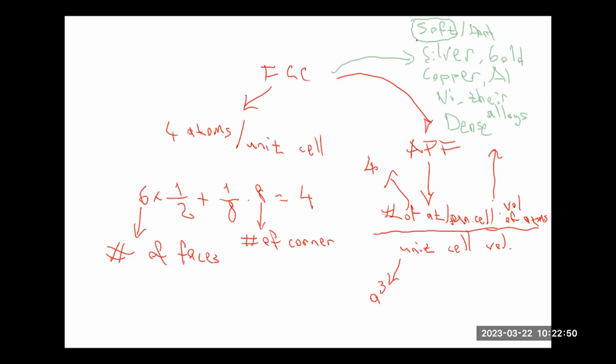So dislocations move very easily. And the critical resolved shear stress values for the single crystal are maybe between 0.1 to 1 megapascal. So it's very, very soft. But they're ductile, right? But we need to harden them. We need to increase their hardening, their strength levels.